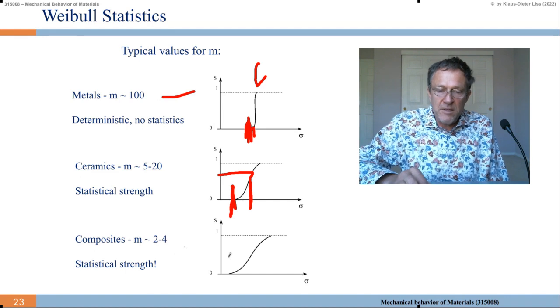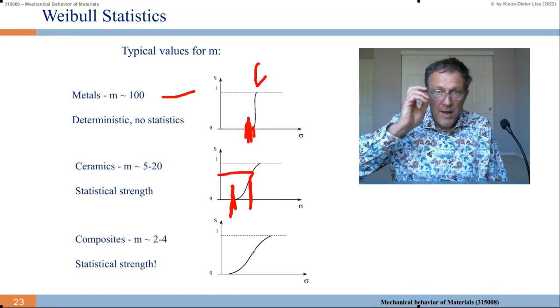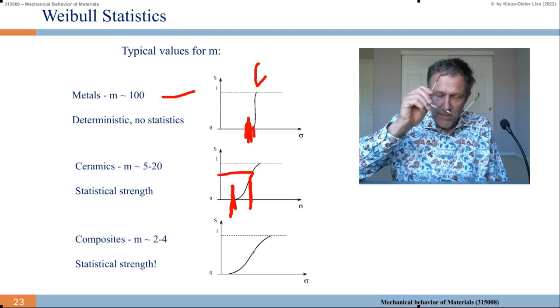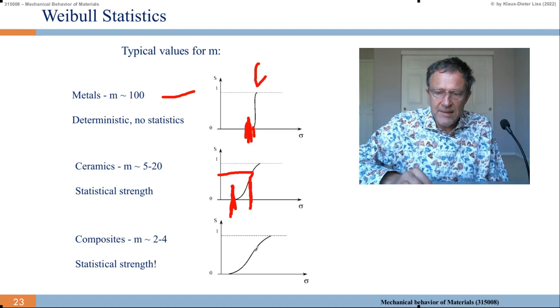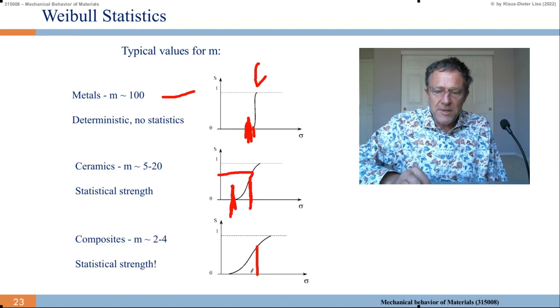And for composites, it's 2 to 4. Also for brick and chalk and so. So that's why you don't build an airplane out of brick or chalk. See, here's a 63%, so this would be our sigma 0. And you cannot go close to sigma 0. Even half at sigma 0, you still have some relative high probability of failure, which you do not want to have in a high engineering device. So you have to design for really low stresses.